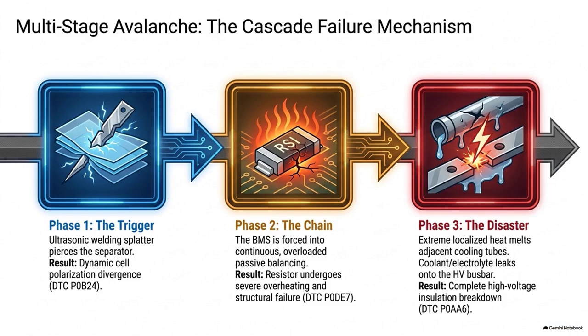When it hits that, the actual structural integrity of the cathode lattice just starts to collapse. It literally releases oxygen, and at the exact same time, the electrolyte is oxidizing against the cathode. So you suddenly have an oxygen-rich, highly reactive environment with intense localized heat. Which is basically the recipe for a bomb. It is the fundamental pathology of thermal runaway. Yeah, it's a chemical breakdown triggered entirely by a blind spot in the balancing circuit.